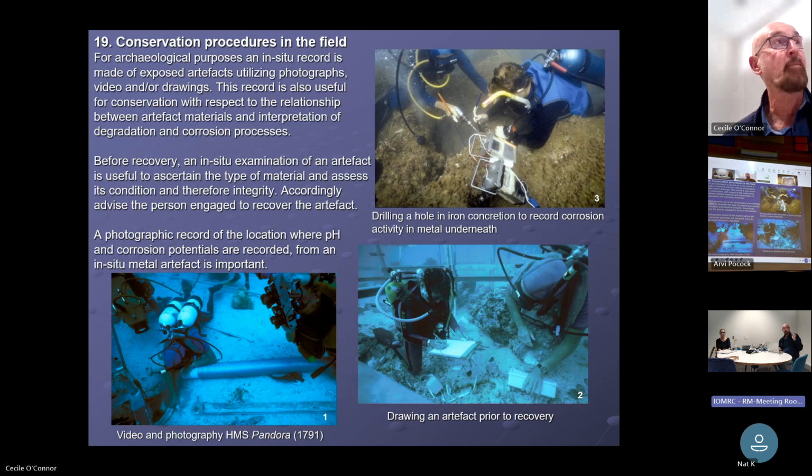And then we put in a platinum probe, which gives us a small measurement on a multimeter, a microcurrent. Those two readings can be related, and that will tell you what's happening to that object, whether it's actively corroding or whether it's immune. If there's other metals nearby, so if you've got copper and say you've got iron, usually the iron will corrode in preference and actually protect the copper. Similar with silver coins, like on my shipwrecks, those coins largely have been protected by the presence of lots of cannons and cannonballs and so on.